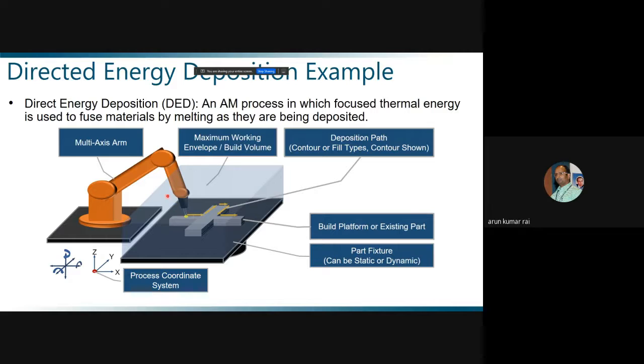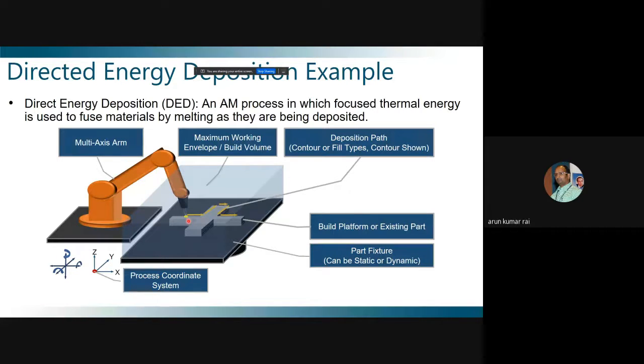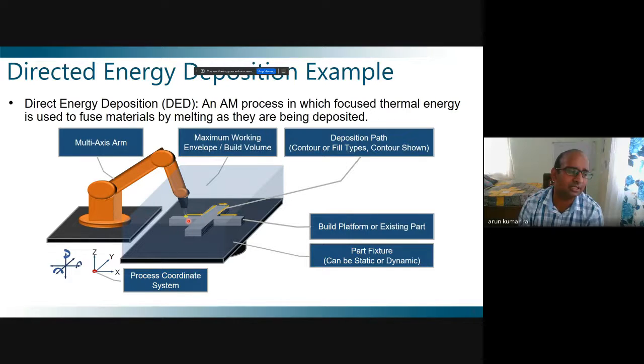And this has one more advantage. Suppose in one pass you are printing one layer, how much maximum thickness can you achieve? In powder bed fusion, the maximum thickness you can go is 50 micron to 100 micron. Beyond that, it will create a lot of defects in the material, and I will discuss that later. That is a disadvantage of the powder bed. But in direct energy deposition, you can print at least 500 to 600 micron thickness at one time.